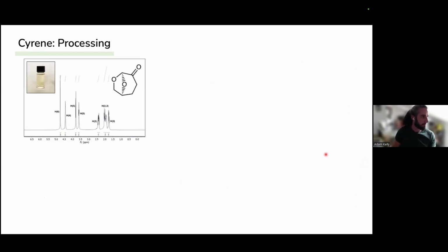Now, if we do the same thing for whatever this degradation product is, we run the process again. So this is the mass of the solvent, this is it starting again, the mass of the solvent against temperature. And in the video, we see some boil off of the solvent, which is the plain cyrene component that's gone. And then there's clearly a solid component left, and that kind of combusts and turns into an ugly black donut. So we clearly have two components in here, one of which is cyrene itself, and another is some sort of solid that is dissolved inside the cyrene.